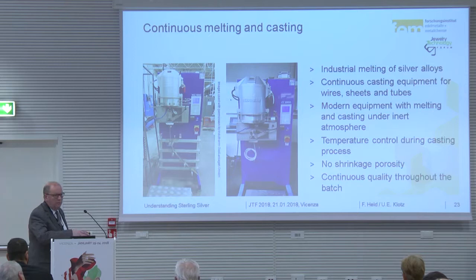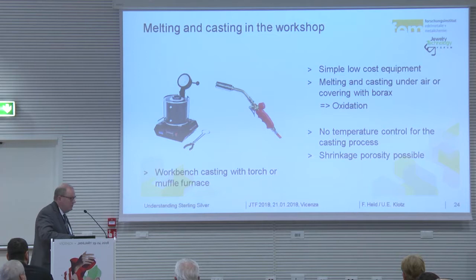If we look at melting and casting in workshops, you have small ovens or a torch. And it's simple equipment. It's melting, casting under air, covering with borax, and we get oxidation. No temperature control, shrinkage porosity is possible.